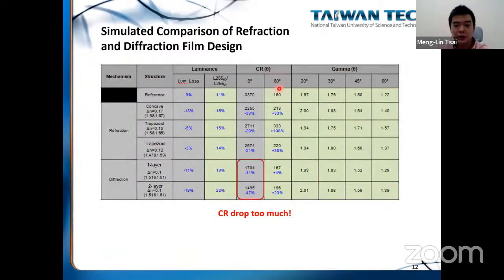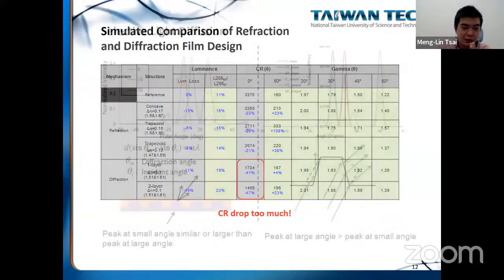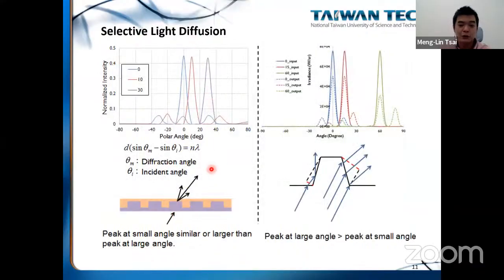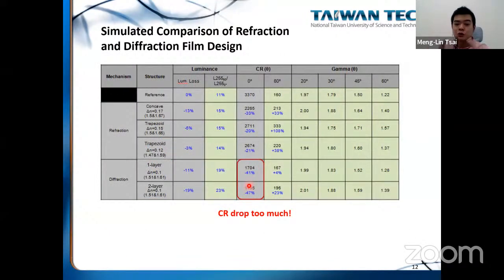Our goal is to increase the contrast ratio at large angle without sacrificing too much of the contrast ratio in the normal direction. But as we talked about in the last slide, for the diffraction, there's almost no selective light diffusion. So the light leakage in the large angle direction will be diffracted back to the normal direction. This will induce a large drop in the contrast ratio in the normal direction. So for this type of design, there's not much improvement in the contrast ratio at large angle, but you are sacrificing too much contrast ratio in the normal direction.